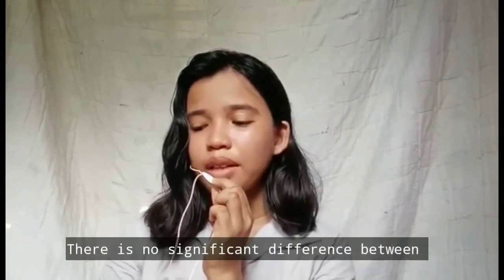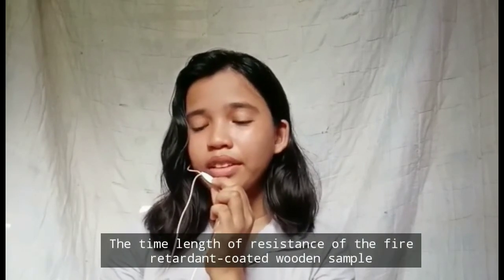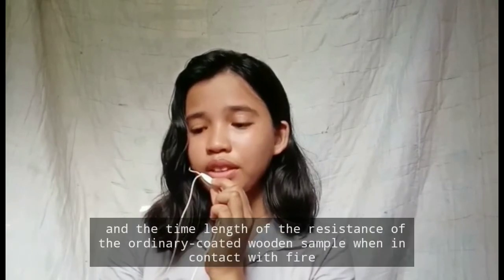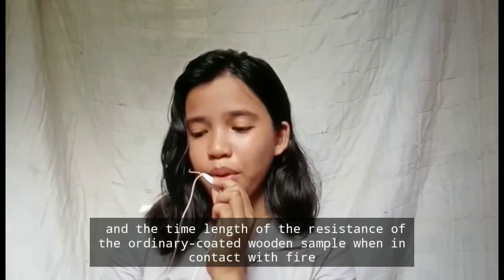Conclusion. In general, based upon the results of the experiment of the proponents, there is no significant difference between the time length of resistance to fire of the fire retardant coated wooden sample and the time length of resistance of the ordinary coated wooden sample when in contact with fire. There is a very small probability that the results of these trials are significant, but that does not mean that the coating made from aggregate sand and Hibiscus rosa sinensis is ineffective. The coating is quite effective for fire resistance when applied to a wooden sample. This also features a great potential to be used as eco-friendly, while at the same time, it preserves the environment.